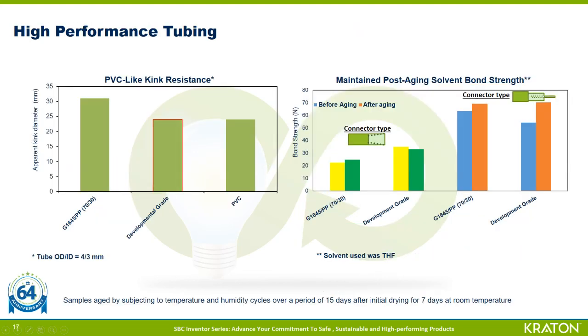Here we have shown data on kink resistance and solvent bonding of G1645 polypropylene blend, along with a new polymer grade that we developed specifically for tubing applications. As you can see, this development grade shows excellent kink resistance, which is really at par with that of PVC.